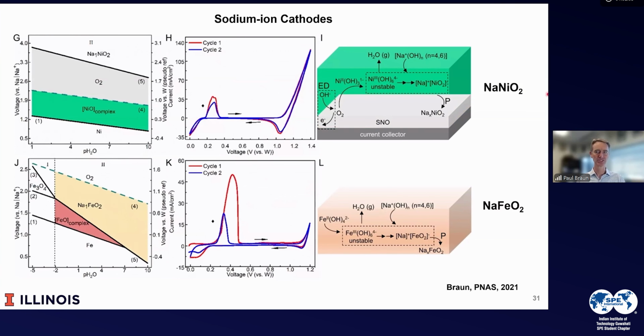The sodium nickel and sodium iron oxide are a little bit more complicated. There actually is no thermodynamic stability region for the sodium nickel oxide. And so while we can grow it, the Coulombic efficiency is quite low. There's a lot of oxygen evolution during plating. The sodium iron oxide will grow. It turns out it doesn't grow very well. Also, the reaction is more complex. It involves an unstable intermediate, which then has to collapse to form the sodium iron oxide.